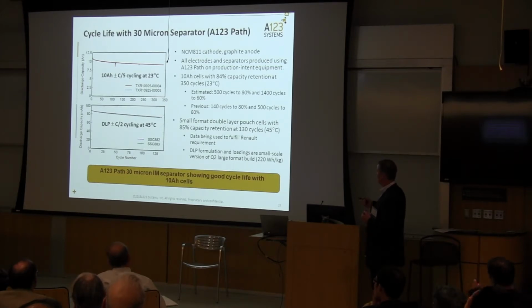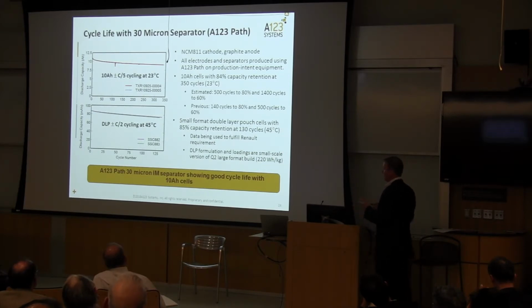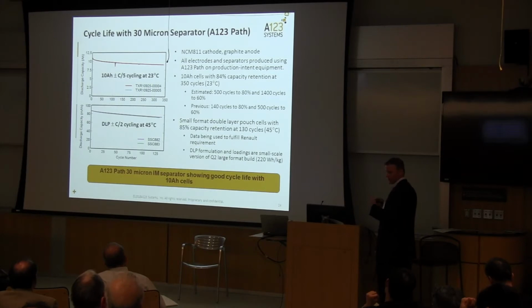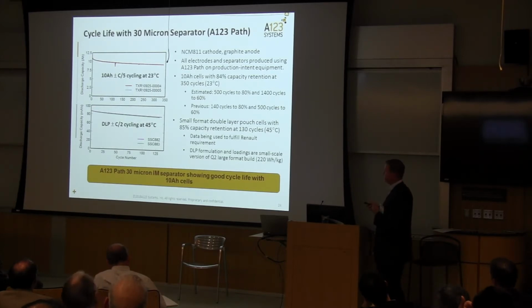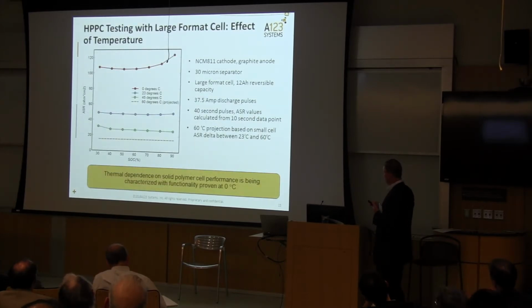And then again, we started testing at higher temperature. The rate performance is actually much better here, but we have this same issue that was shown earlier. I think you were pointing this out, that as you go to higher temperatures, we have these side reactions that can happen that can help degrade it. So we're seeing the same thing here, and we think it has to do with actual stability of the ionic conductor in these systems. This is actually really interesting as well.